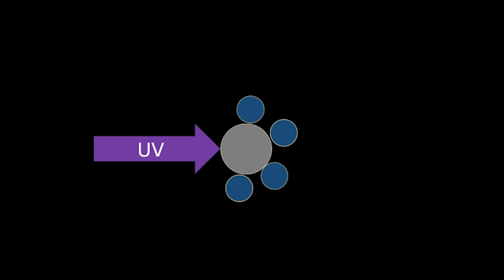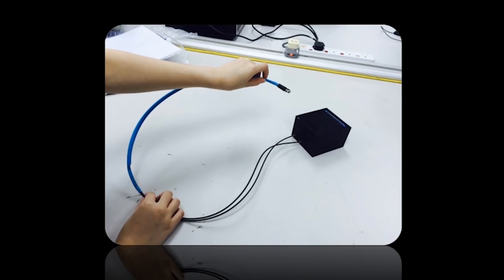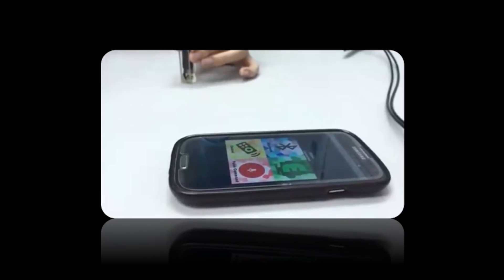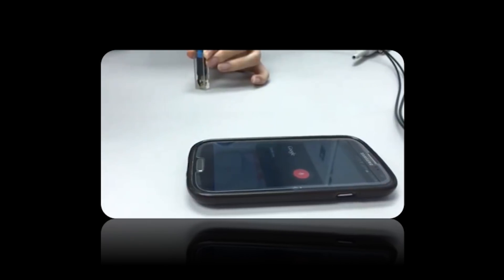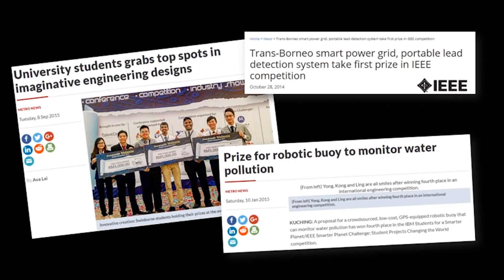When there are specific ions of a specific size present in a liquid environment and you excite these quantum dots, they transfer their energy and release less fluorescent light. This means we could use this to create optical fibre-based sensors that can be used to monitor heavy metal ion concentration in water. This was a project I did back when I was studying in Swinburne University with my supervisors. We created an app, used optical fibre to isolate the electronics, and even used voice control. We created this project and won numerous awards.